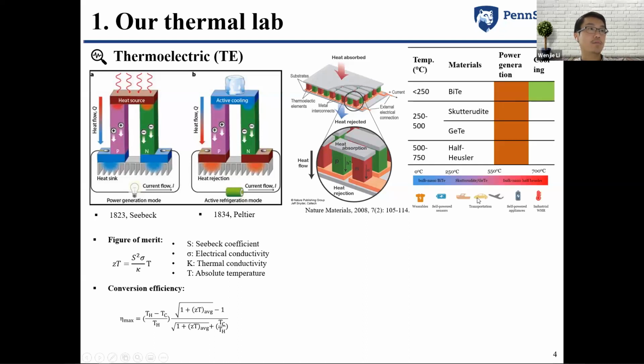So in our lab, we mainly focus on four types of thermoelectric material systems, like bismuth telluride. Mostly it is targeted for applications below 250 degrees C, covering both power generation and cooling purposes. And for the medium temperature range up to 500 degrees C, we have skutterudite and germanium telluride materials.